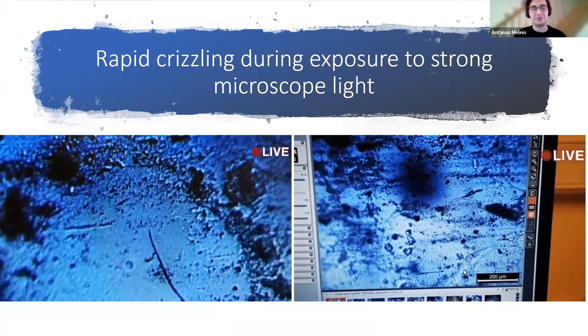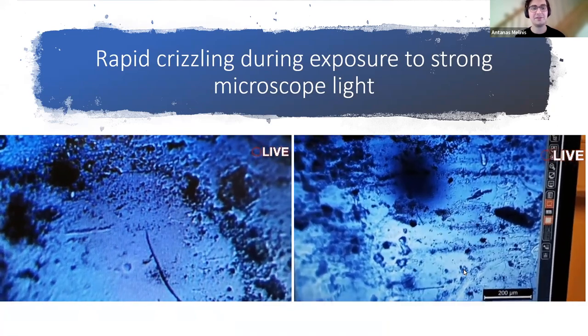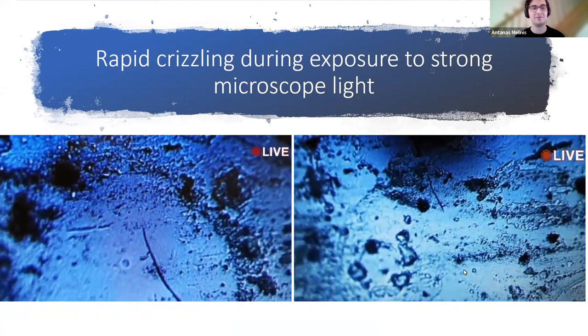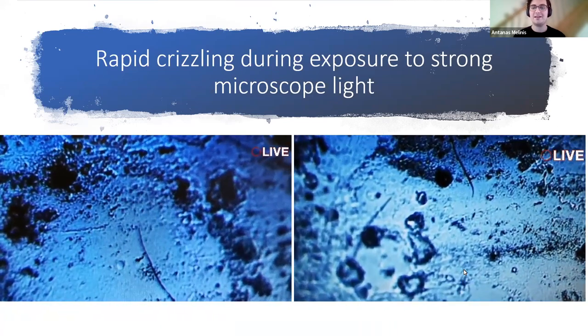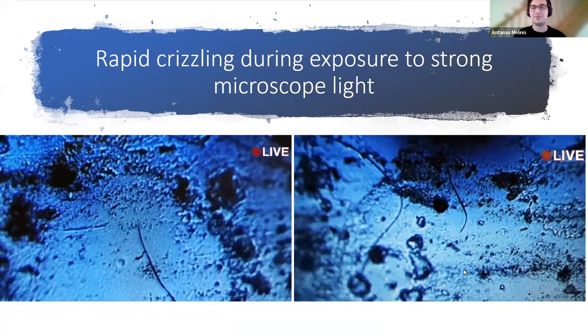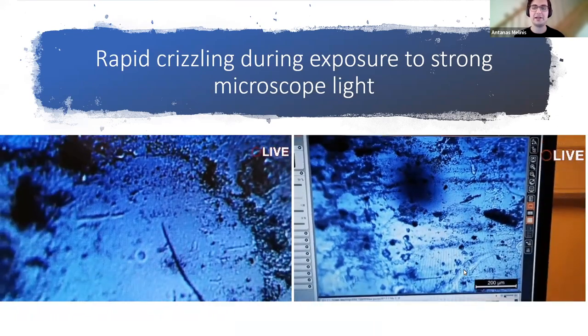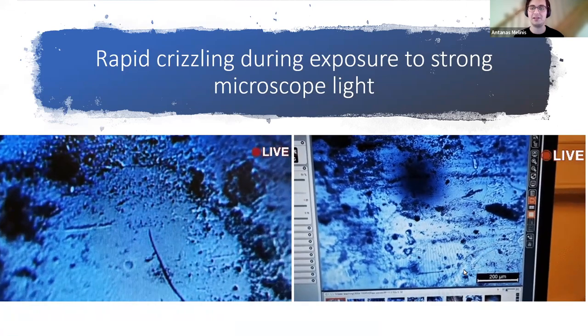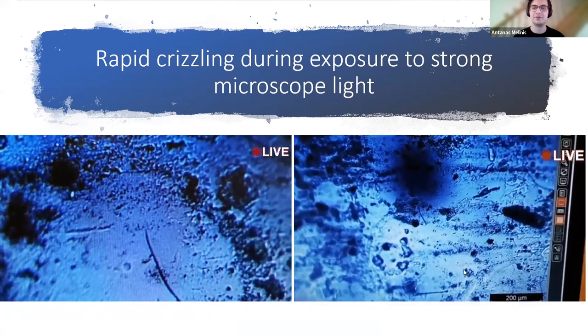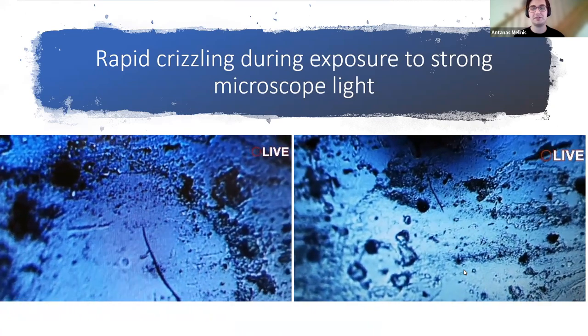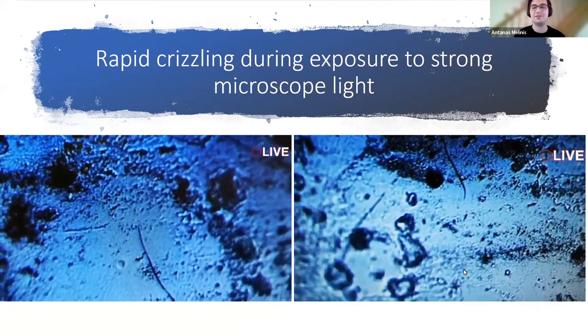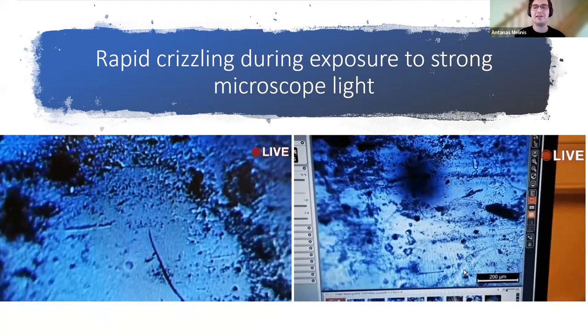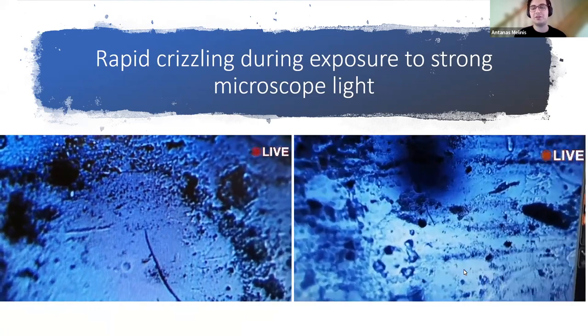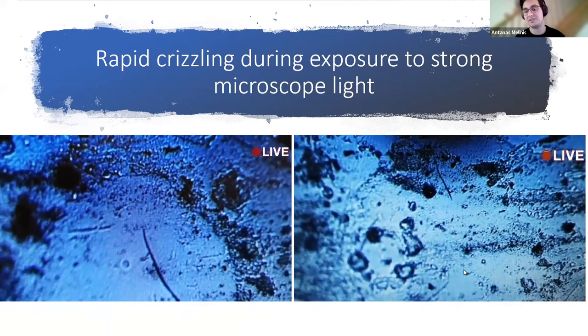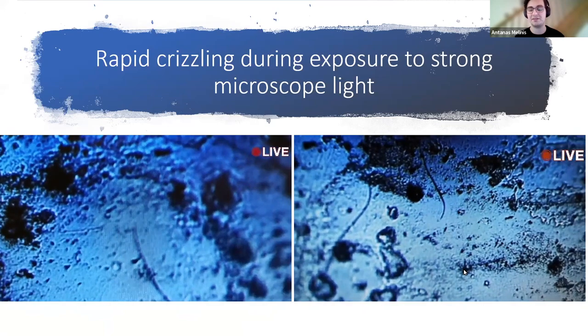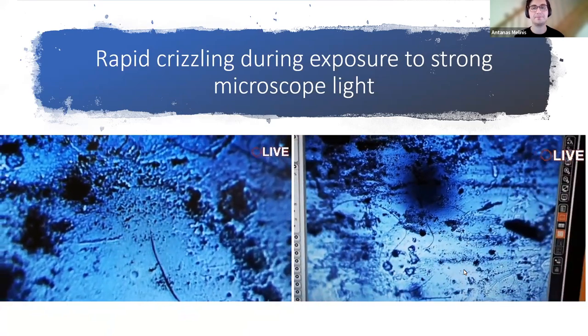One of the most interesting findings was crizzling in real time, which happened during exposure to strong microscope lights on one of the pieces exposed to water, where this action of spot heating with the lamp was enough to set off a chain reaction where the surface dried and ruptured under stress in a single location, and then the cracks spread through the entire glass within a mere 2 minutes. So you can see this reaction in real time, with some cracks appearing almost instantaneously and some sort of creeping along the surface. So it demonstrated that crizzling could be rationalized as an event or a series of sudden events rather than simply a long process.